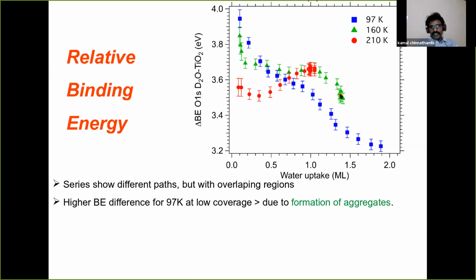But the most important question is what happens when you go to 210 Kelvin. It starts with pretty low values, and when you start growing, the values are not decreasing. It initially decreases, and then goes to a value which is very low compared to the other two. Then when you go to one monolayer, it starts increasing. But this part is not very obvious, because once you pour more and more water molecules, the extended network should start, and it should keep on decreasing. Why, for the lower coverages, are the binding energy values quite low? That is not clear. So this is one of the main motivations from the theory side, to explain why these things are happening.